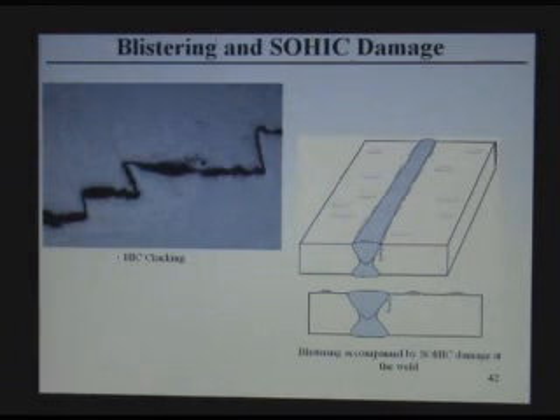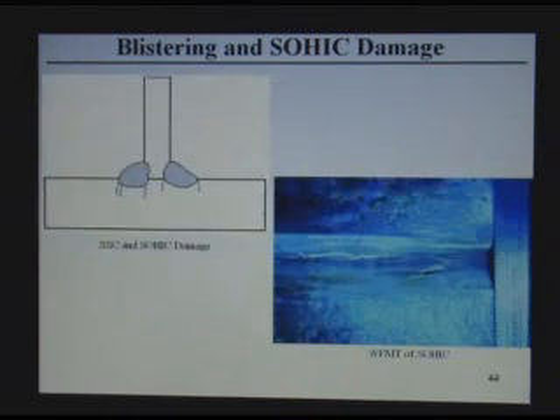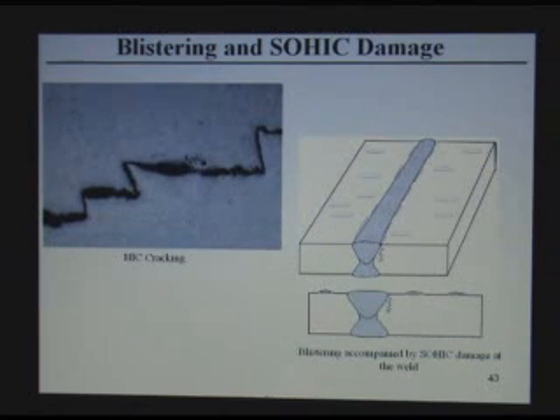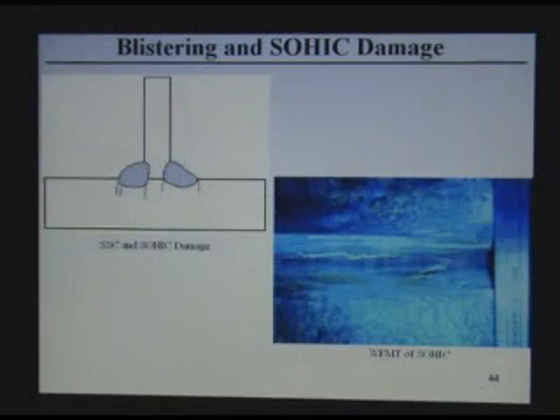This is stepwise cracking and hydrogen-induced cracking, where cracks occur in the metal. And if the cracks propagate perpendicularly this way, they call it SOHIC, stress-oriented hydrogen-induced cracking. This is an example of sulfide cracking and stress-oriented hydrogen cracking. And the technique now to find such mechanisms in shutdowns is wet fluorescent magnetic particle testing, which is very sensitive and can find cracks in the heat-affected zone of welds.